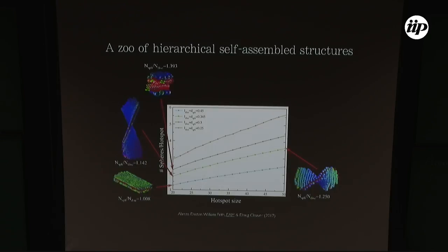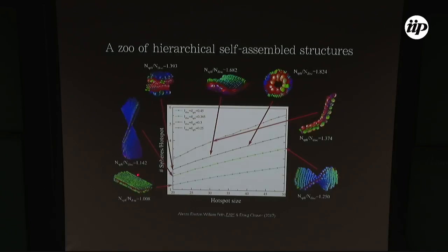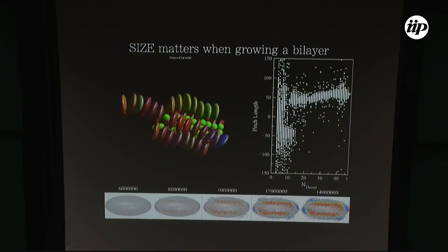They'll have negative Gaussian curvature. And so you can see as you grow it, it begins to have negative Gaussian curvature, and if you grow it even more, you end up with a tube. And for really, really thin disks, you get these double helical structures. So there's a central fluid core, and you have very tightly wound helices. So you can get this entire arrangement just from one system, but I'm going to focus on these helicoidal structures.